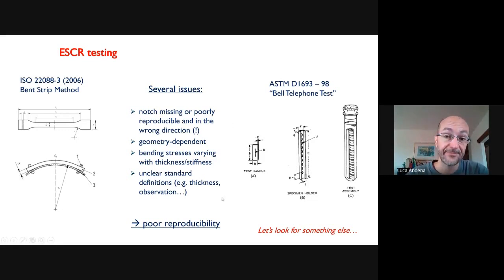So in addition to that, the test is very geometry dependent, meaning that the bending stress that you achieve initially depends on the thickness of the samples and on the stiffness of the sample.